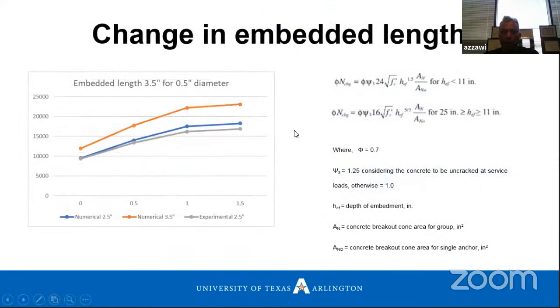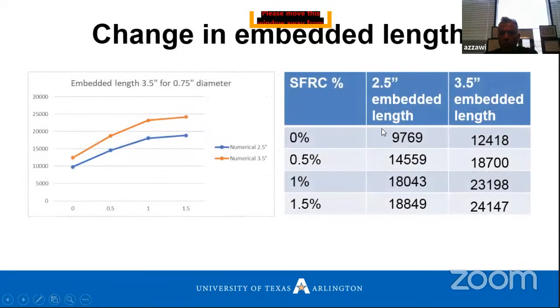Change the embedded length, and its effect is clear. If we change the embedded length from 2.5 inch to 3.5, we will see there is a difference, as we see here. Increasing the embedded length will increase the strength of the anchor bolt in tension. See how much it's increased. 2.5 inch embedded length gives us 9.7 kips. 3.5 gives us 12.4 kips. And increasing the fibers also will increase the strength if we increase the embedded length, as we see here. So more embedded length will help to increase the